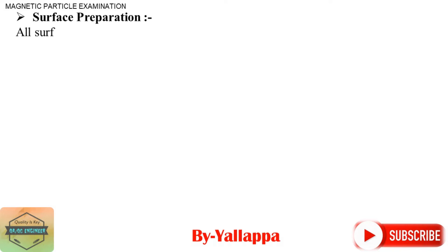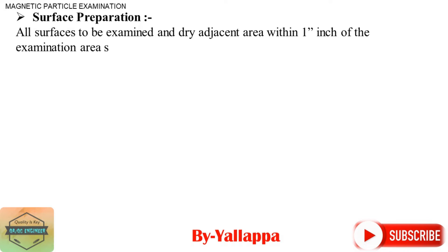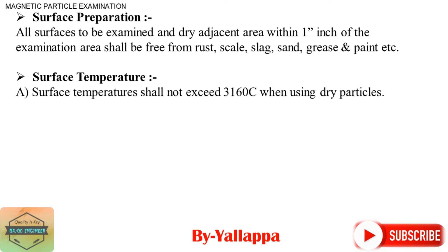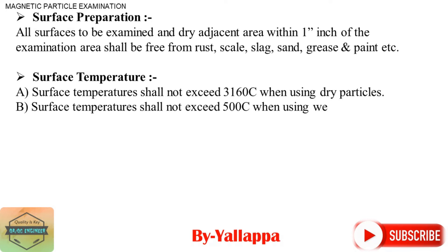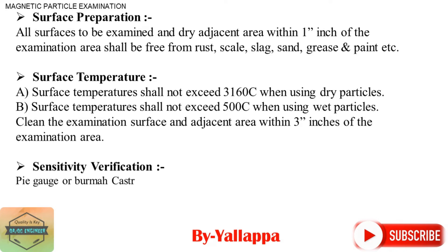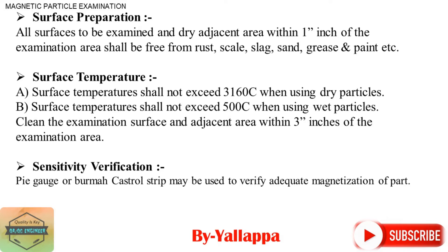All surfaces to be examined and dry adjacent area within 1 inch of the examination area shall be free from rust, scale, slag, sand, grease, and paint. Surface Temperature: A. Surface temperatures shall not exceed 316°C when using dry particles. B. Surface temperatures shall not exceed 50°C when using wet particles.